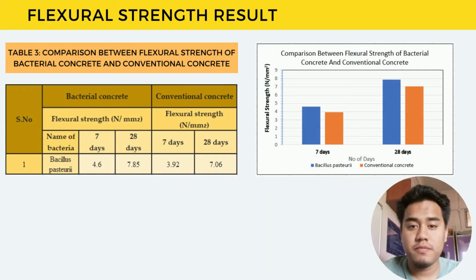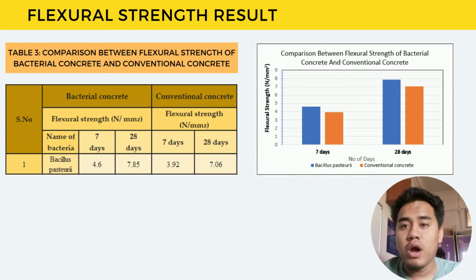Flexural strength result. Table 3 shows the comparison between flexural strength of bacterial concrete and conventional concrete. One microbial material was tested, which is Bacillus pasteurii, along with conventional concrete. The results show that Bacillus pasteurii has the highest flexural strength during 7 days and 28 days of curing, which are 4.6 Newton per millimeter square and 7.85 Newton per millimeter square, respectively.